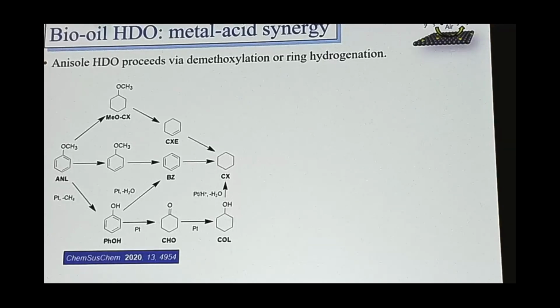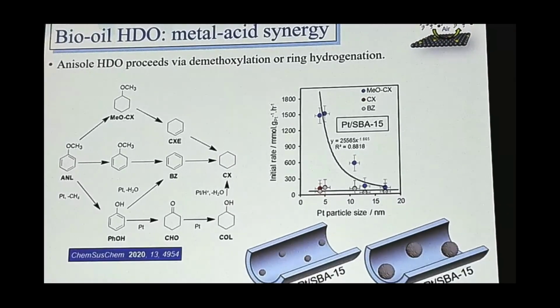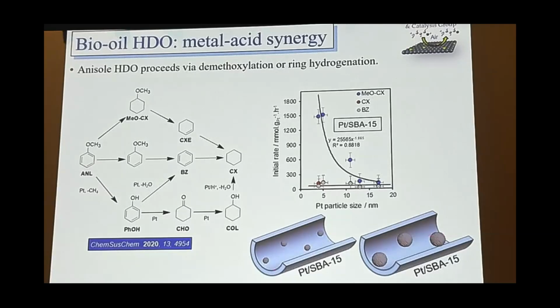It's that story that I really want to talk to you about on this next slide, is really how we can design a catalyst with metal thrifting in mind. So many catalysts that are used for hydrodeoxygenation often use quite high metal content. So typically you might be looking at, say, 1 to 5 weight percent precious metal, because the catalyst itself isn't optimized for the process. So what we've been looking at is how we can optimize platinum loading and working with highly dispersed metal nanoparticles in order to improve process efficiency.